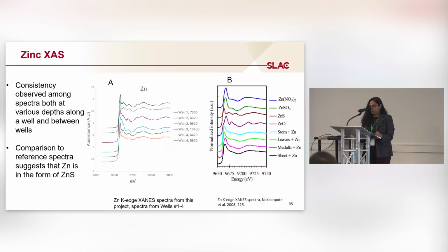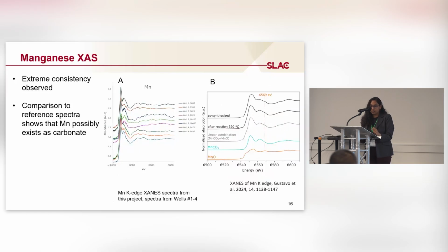Zinc XAS is also a similar story, and from comparing to the reference spectra, it looks like it is zinc sulfide. We were able to confirm this by looking at how far out we are able to get in our XAS spectra. If we get a good amount of data, we can do more analysis on it, called EXAFS analysis, to confirm the structure. In this case, we were able to do that, and we confirmed that it was zinc sulfide indeed. And for manganese, it looks like it is manganese carbonate.